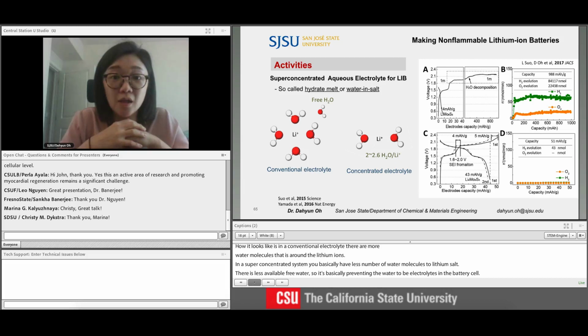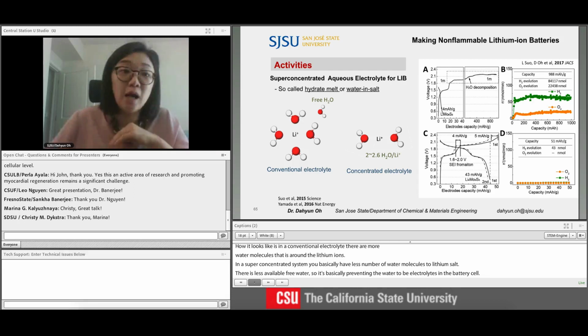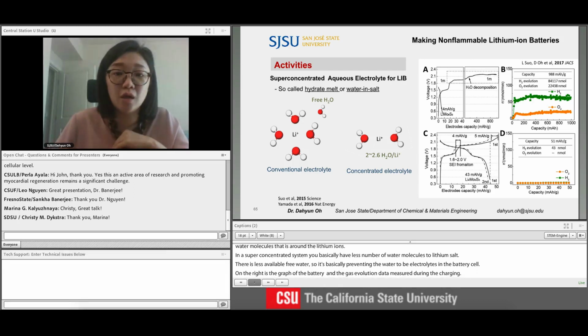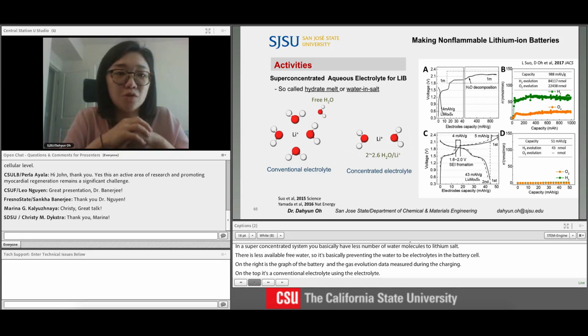On the right is a graph of the battery voltage profile and the gas evolution data measured during charging. On the top is a conventional electrolyte using a 1 molar electrolyte. Then you will see hydrogen and oxygen evolution. But on the bottom, once you switch to the concentrated electrolyte, you are seeing suppressed evolution of these gas molecules.